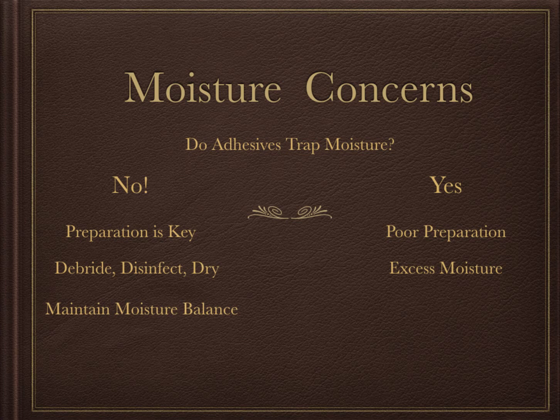Unfortunately, we get a lot of calls for, my horse is in a wet environment, how do I put adhesive on to keep the moisture out? That's a real challenge, because if you can prep it and get it on there when it's dry, then excess moisture is not as big a factor unless they're standing in it. If they're wading through creeks or walking through wet grass, that's not going to have an effect. But if they can stand in something that submerges the foot, then you've got a problem.